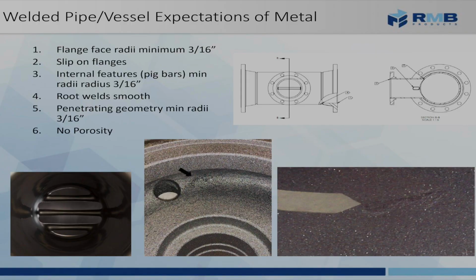Some of the important features of the metal for it to be rotational lineable are that there are no sharp corners. So the resin's not going to flow well over sharp corners. So it has to be prepared so that any internal and external radii are about a 3/16 minimum curvature. For slip-on flanges, we're going to need to make sure they're welded so that there's no crevice both on the inside and the outside.